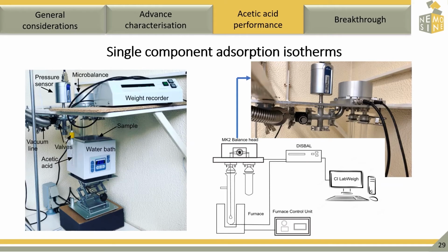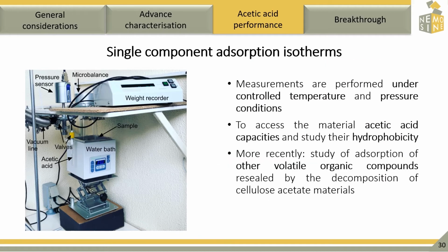We also investigate the adsorption of acetic acid and water as a single component, and for this we use a microbalance, and the measurements are performed by evaporating the corresponding vapor into the sample, which is placed inside the microbalance, and recording the mass and pressure changes over time. These experiments are performed under vacuum and at a temperature of 25 degrees, maintained with a water bath. These measurements are performed under controlled temperature and also pressure. And this setup allows us to access the materials' acetic acid capacities and also study their hydrophobicity.